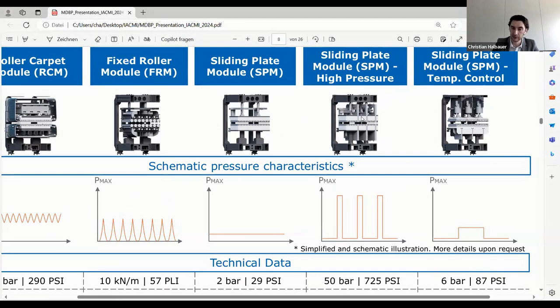The high pressure model, again, I'm going to introduce it in greater detail a little bit later on, does have high pressure beams where we can apply pressure levels of up to 50 bar. And then we also do have one for temperature controlled cooling,